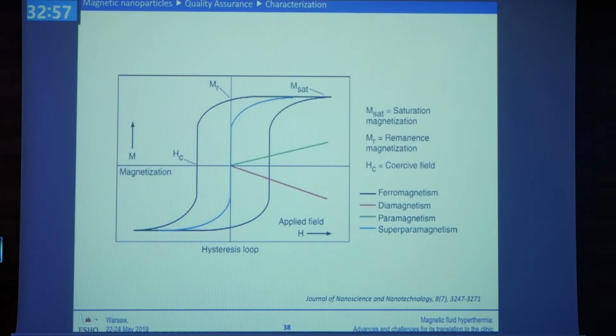The only cases where we have the same effect if we increase the magnetic field or we reverse it are these green and red lines, which are diamagnetism and paramagnetism, okay? And there is another kind of materials which actually come from ferromagnetism, and they are called superparamagnetic materials, where we don't have a hysteresis loop, or this loop is very small. We say that the coercive field, which you can already see on the screen here, of these materials is very small. But we'll talk about that later.